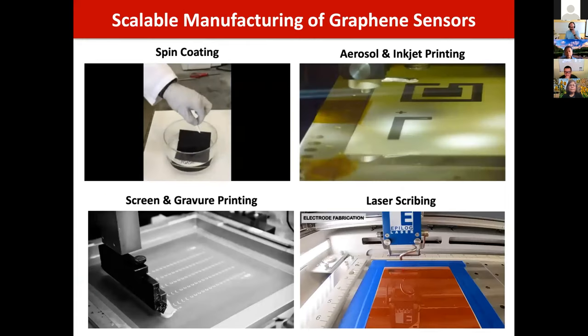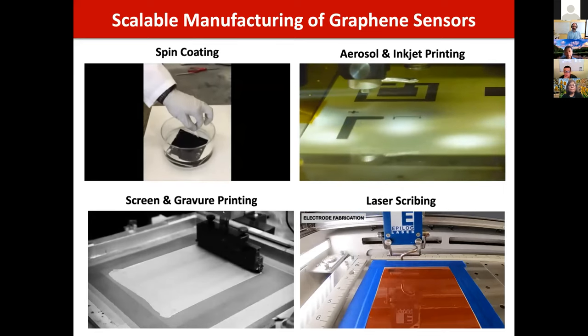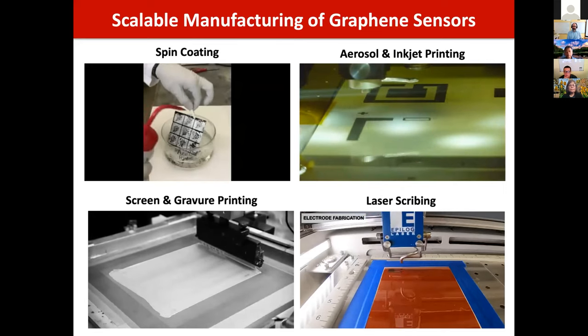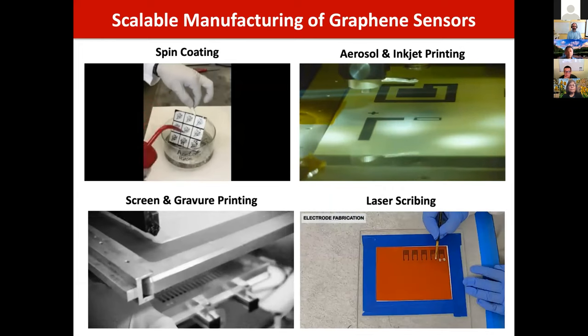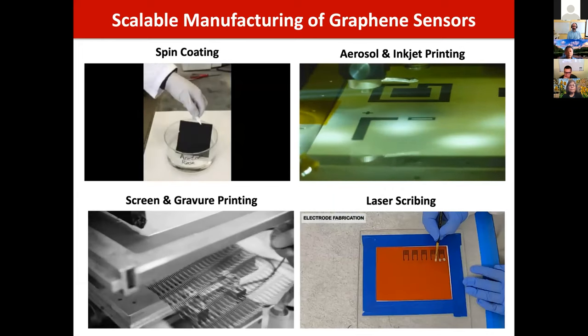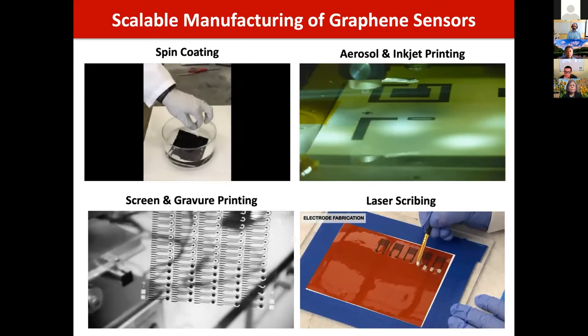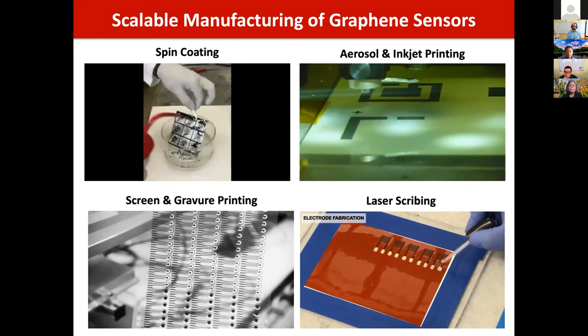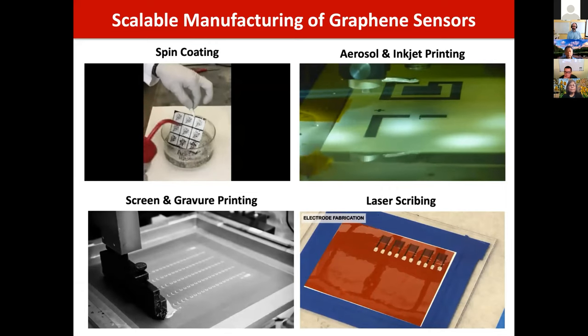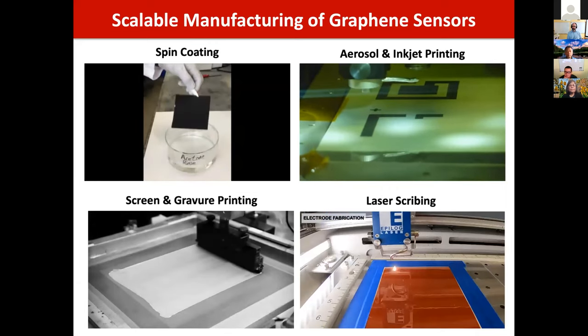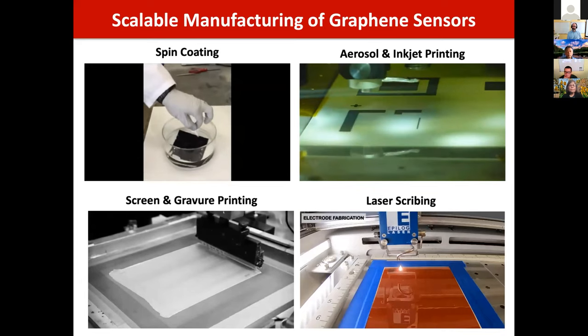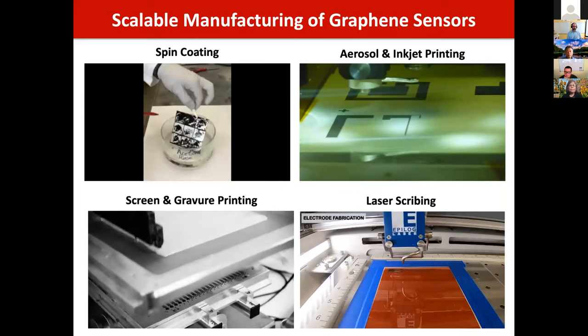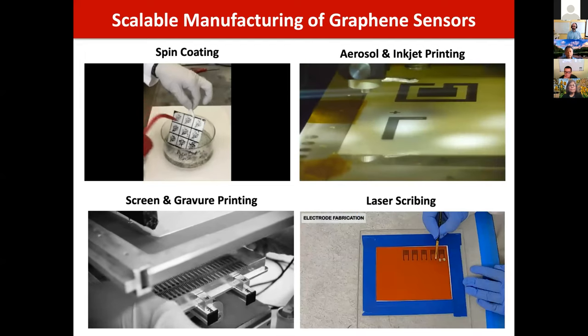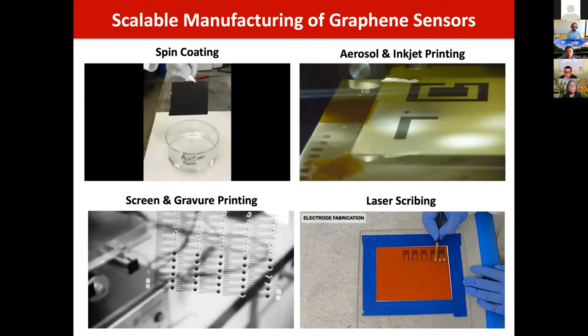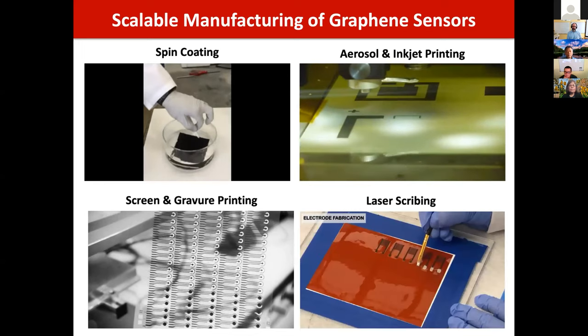So here's some of the printing technologies that we use for graphene. We started out just spin coating it here in the upper left-hand corner. We'd inkjet a polymer underneath and we could pattern with fairly high resolution on that surface. We've also gone to aerosol and inkjet printing, and those are more rapid prototyping techniques where you can make a sensor and try it out and see how well it's working. And then screen and gravure printing is what we're moving to to get it out the door towards commercialization. This is where you can make hundreds of sensors in one batch, and that's where you can start getting down to the cost of pennies per sensor.